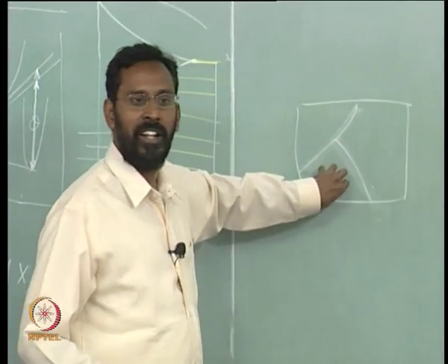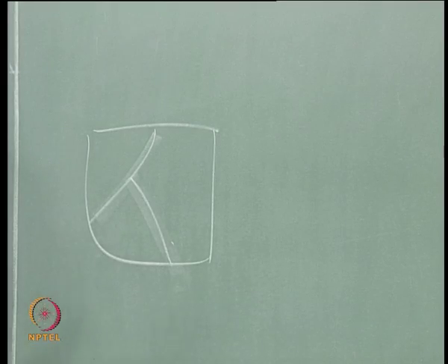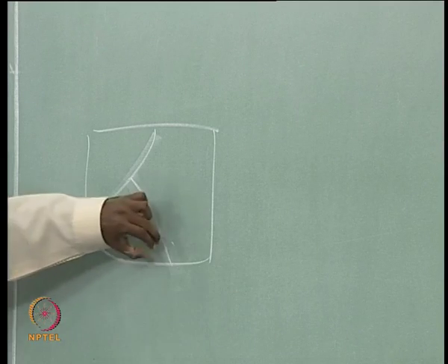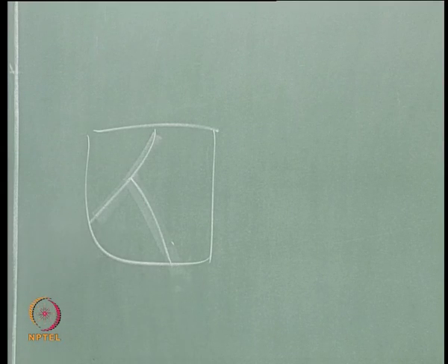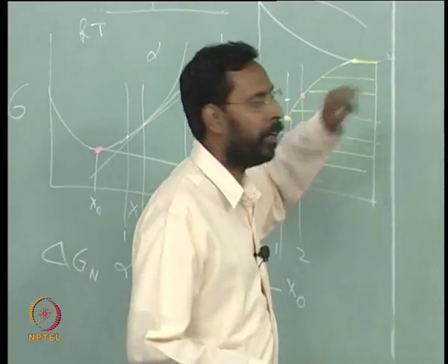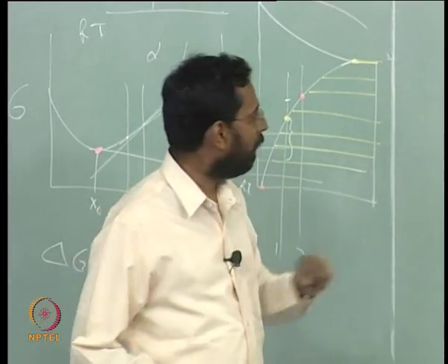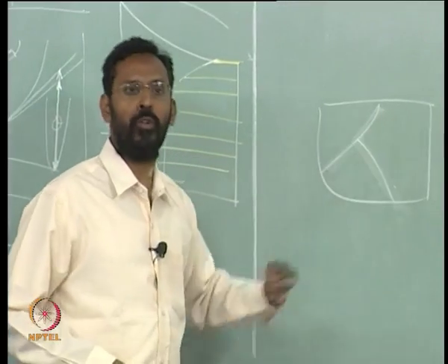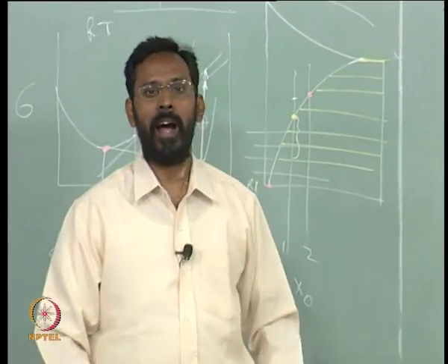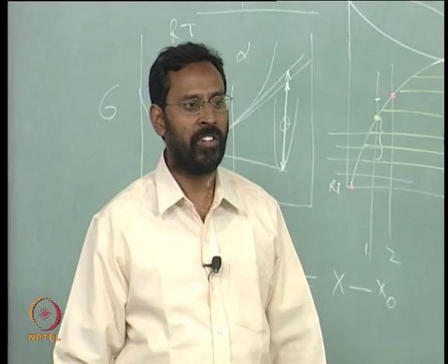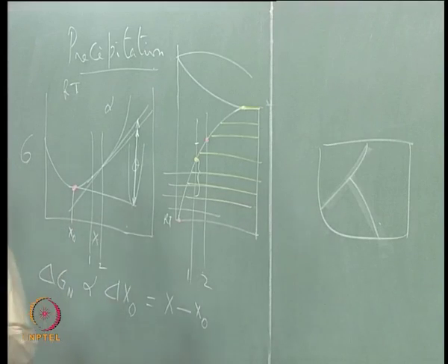So, alpha which is there here will remain as supersaturated because I am quenching it, but the theta which is there at the grain boundaries will remain as theta. Depending on what your alloy composition is, some amount of theta will be there according to the phase diagram. And this supersaturated alpha, which has formed at room temperature when you quenched it, is the one which will start precipitating out.